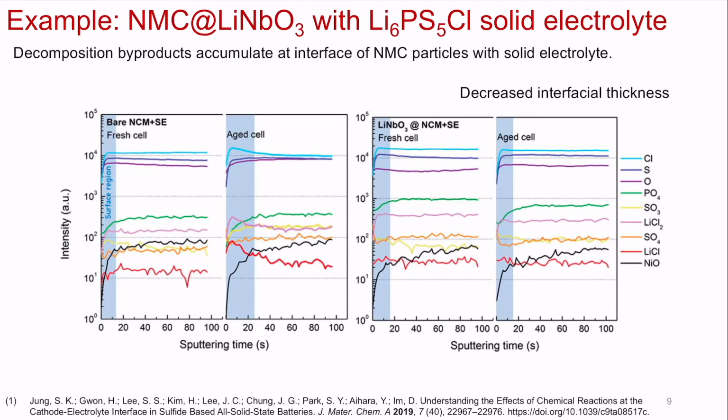So that's in line with the EIS, right? If you have a thicker interfacial area, you would expect them to have a higher resistance. And if your material is not an electronic conductor, then also that means you have higher resistance for the electronic conduction as well as the ionic conduction, right? So it's corroborating what you already see and know from EIS from the beginning, okay?